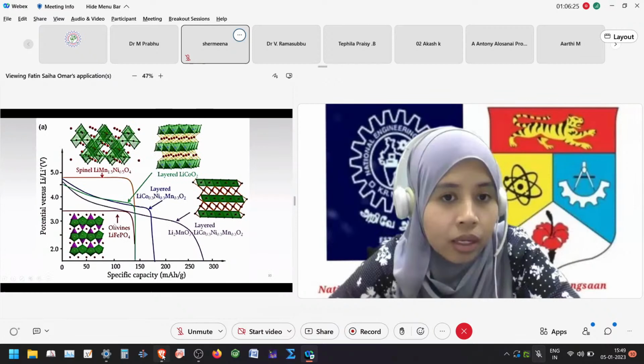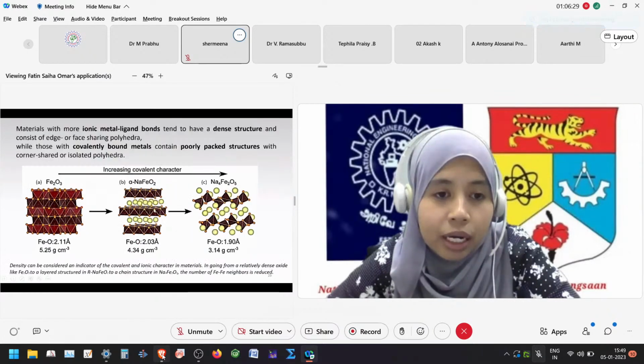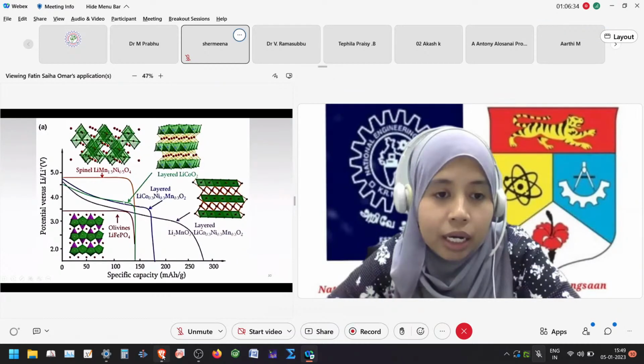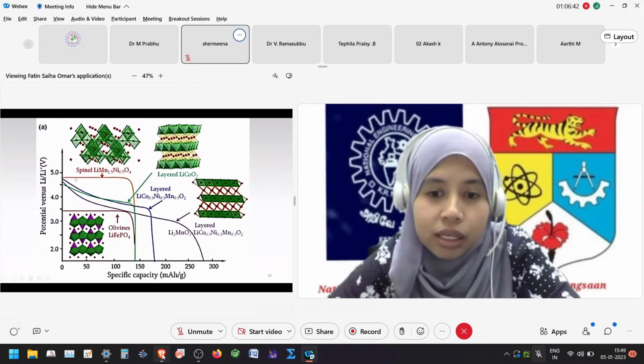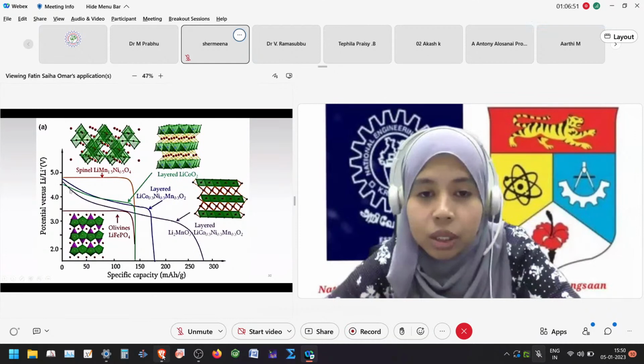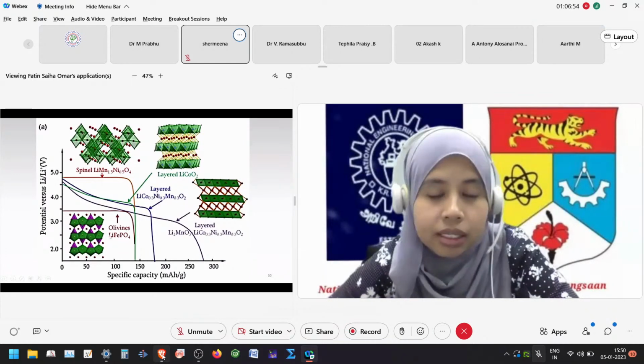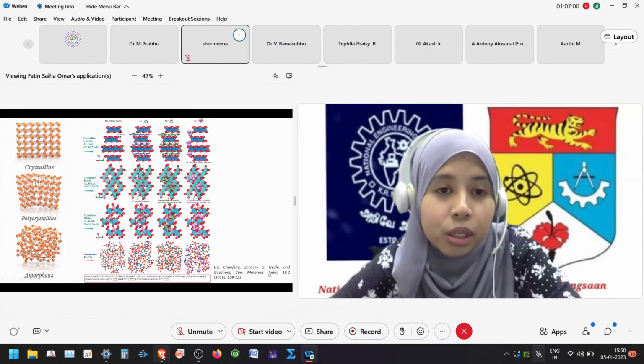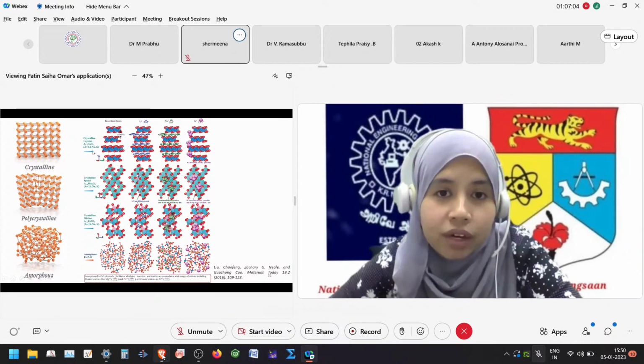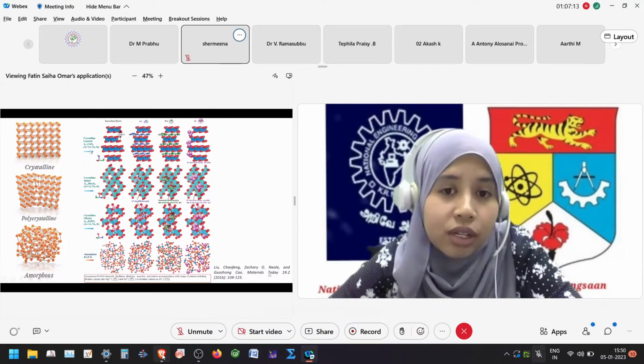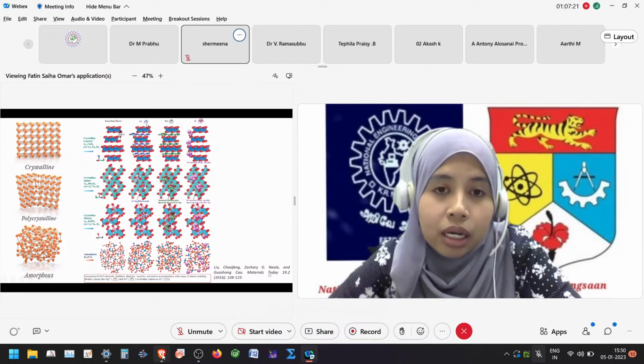Different lattices and different crystal structures can impact the electrochemical performance. For the spinel, the discharge curve tends to be like this, and this one tends to be like this, longer. So we can see different shapes or profiles of the discharge curve for different structures. And in this other work, they varied the crystal structure of the electrode materials and used different types of electrolyte ions. Here we have lithium, sodium, and potassium. Lithium has the smallest ionic radius, which is 0.76 angstrom. Sodium is larger than lithium, and potassium is the largest, with an ionic radius of around 1.3 angstrom.